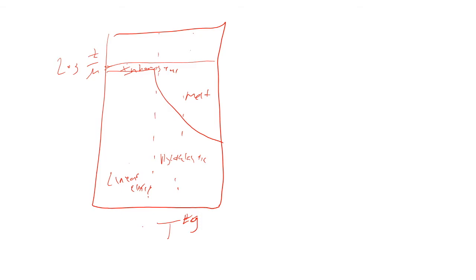We talked about drawing, we talked about the yield surfaces, we talked about crazing, we talked about the effective pressure, right? And it's really kind of self-intuitive. If I have hydrostatic compression, if I have a positive or negative pressure, it's weird. We talk about pressure being opposite in terms of the stress, right? So if we have a negative hydrostatic stress state, it's harder to open up cracks, right? So crazing has a huge change in its dependency based on the hydrostatic pressure, right? And obviously if I have a biaxial state, if I have a dilatational state, it's a lot easier.